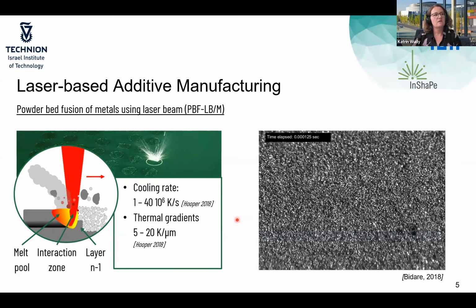And in powder bed fusion, you typically have a specific design of experiments to analyze in which area and combination, typically of laser power and scan speed, so the speed of your laser path at the end, you create a stable processing. And therefore, we conduct a series of experiments, which is shown here for all of these ring-shaped beam profiles. So this means every triangle here is one experimental point, and the other triangles are these state-of-the-art experiment, which is shown here as the Gaussian beam profile.